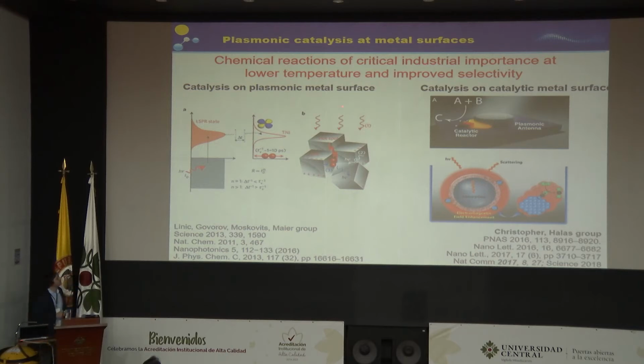In particular, in this case, we have just the plasmonic metal, so nothing else, and we excite the plasmon, and after decay of the plasmon, we have the formation of these hot electrons with very high energy that can interact with the molecules which adsorb on the surface. And this has been demonstrated so far to be able to drive heterogeneous chemical catalysis with much lower energy, and also change selectivity.